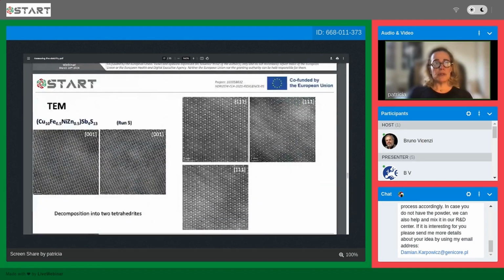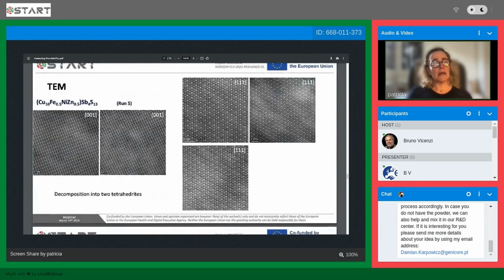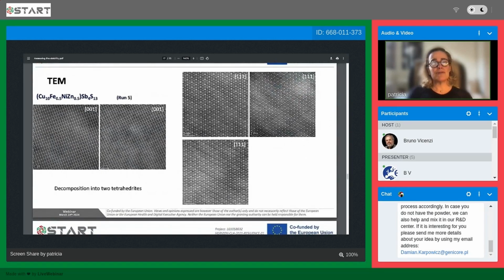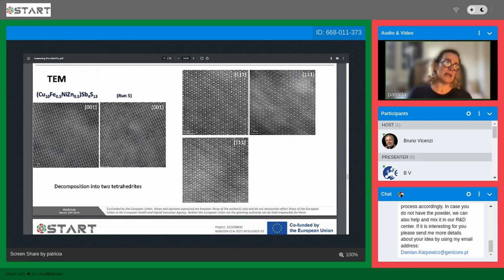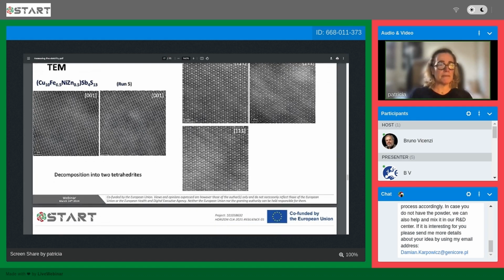Again, if you go to high resolution TEM, you see this contrast difference, which we believe is related to the chemical composition. And this is something we are still trying to understand. So at around the 10 nanometer scale, you see that there are some regions which have a higher mass and regions which have a lower mass. The structure is exactly the same. And we believe that what we're seeing is possibly the initial stages of a spinodal decomposition.